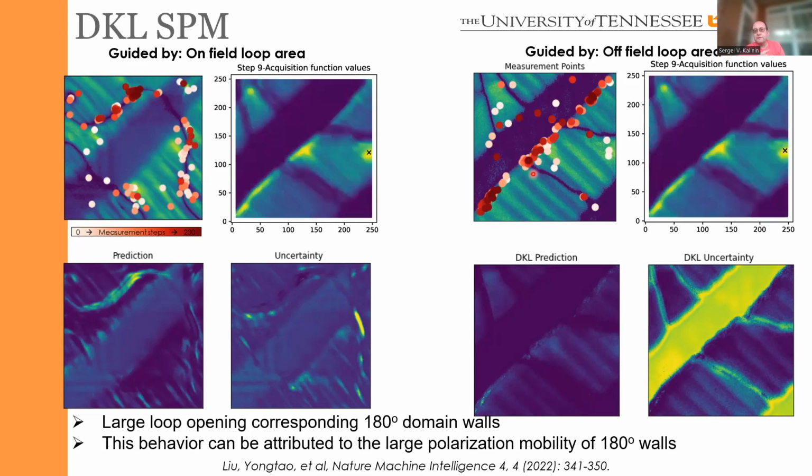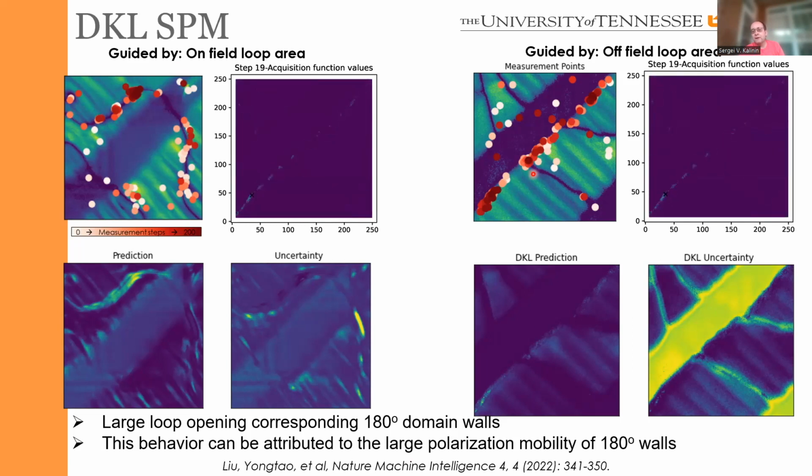This is just a hysteresis loop measurement, something that we've been doing for 25 years by now. So on the material with the very well-defined domain structure, we have only two types of topological defects, ferroelectric walls and ferroelastic walls. And in this case, the microscope produced something that we can readily understand and rationalize.